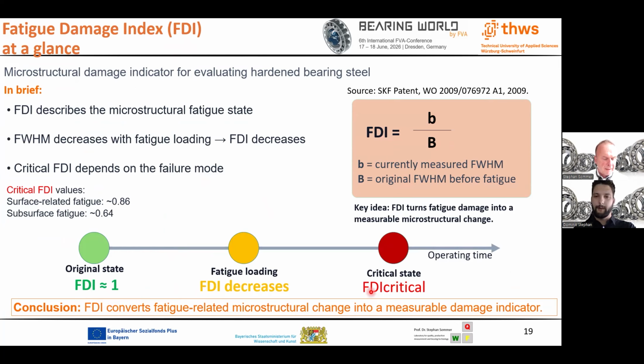The important point is that the critical FDI value depends on the failure mode. For surface-related fatigue, the critical value is around 0.86. For subsurface fatigue, it is lower, around 0.64. So the FDI gives us a way to translate microstructural fatigue damage into a measurable material state parameter.